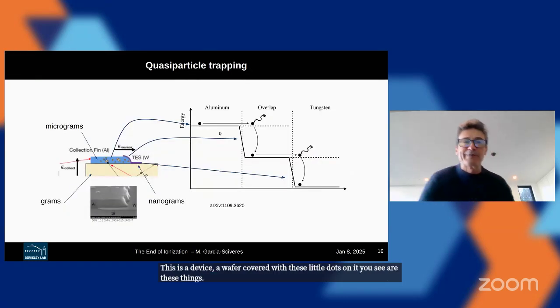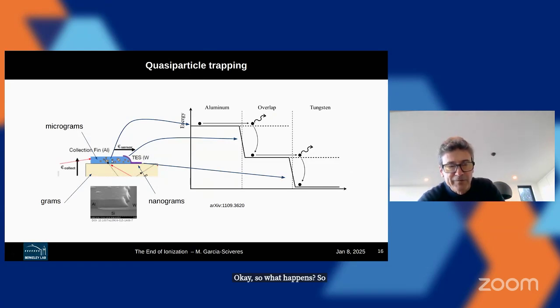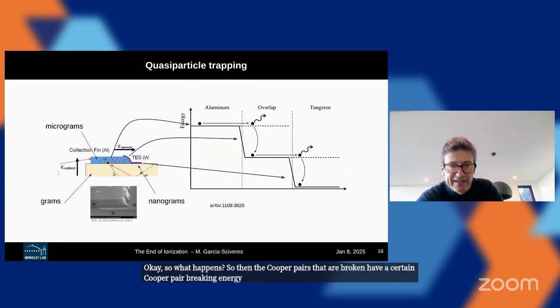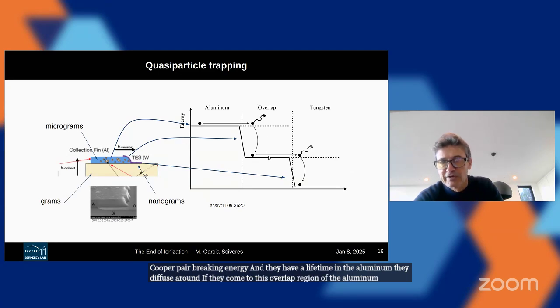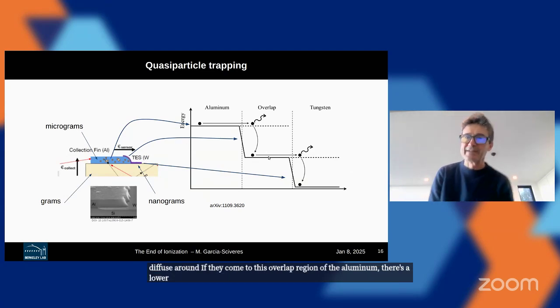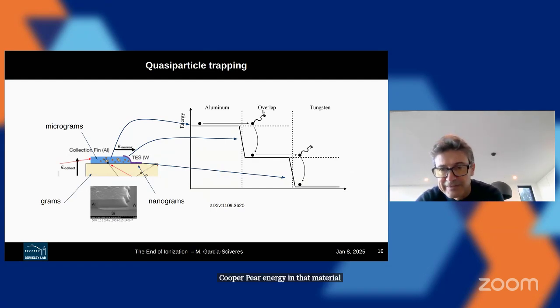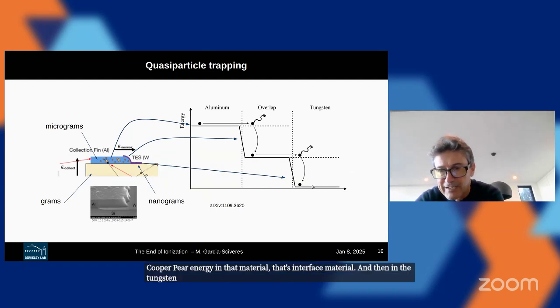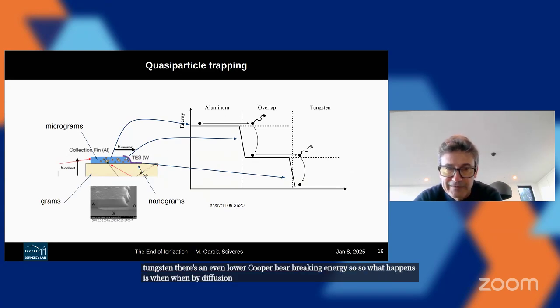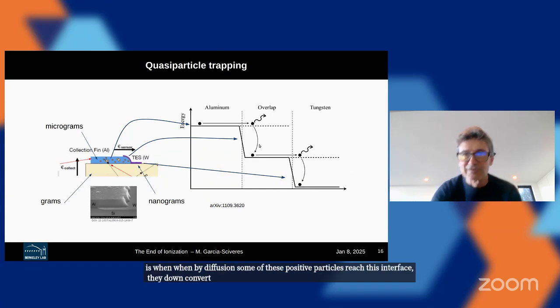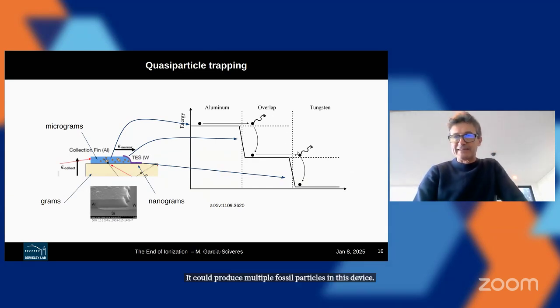Okay, so what happens? The Cooper pairs that are broken have a certain Cooper pair breaking energy, and they have a lifetime in the aluminum. They diffuse around. If they come to this overlap region of the aluminum, there's a lower Cooper pair breaking energy in that interface material. And then in the tungsten, there's an even lower Cooper pair breaking energy. So what happens is, when by diffusion some of these quasi-particles reach this interface, they down-convert, they produce multiple quasi-particles in this device. And then the same thing happens here.